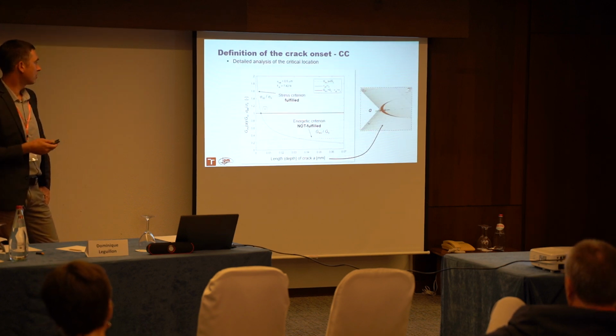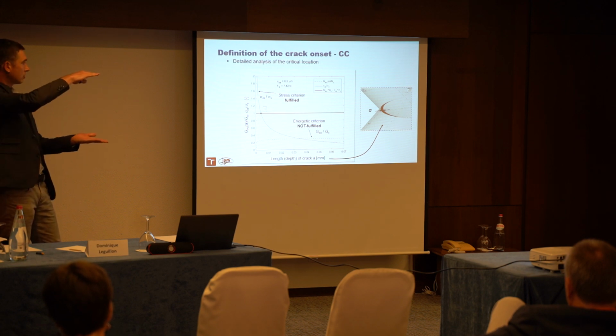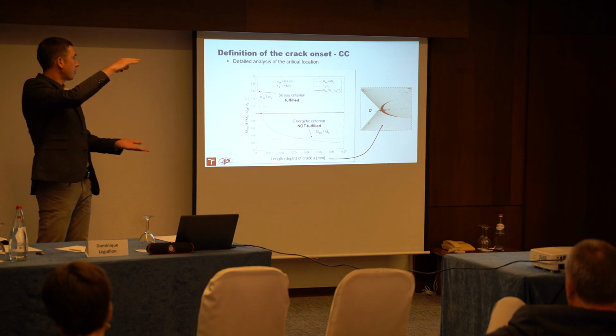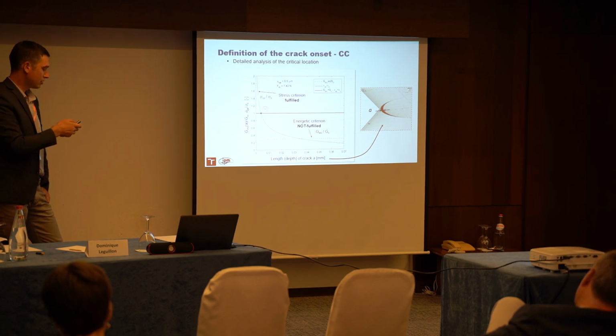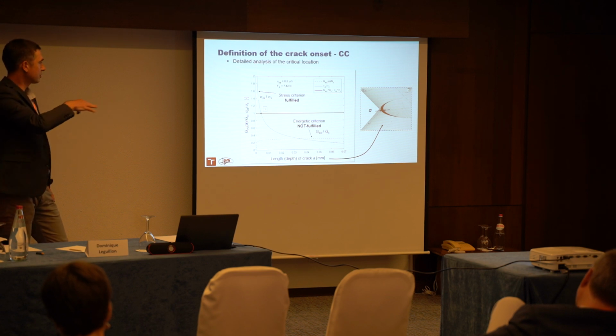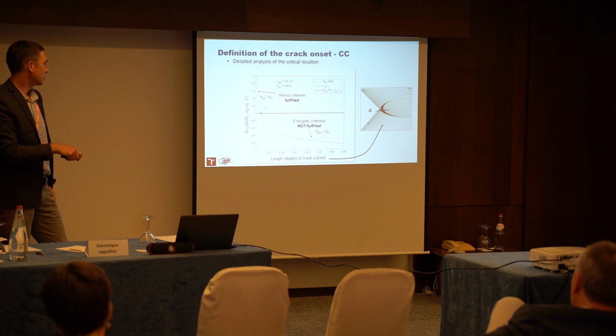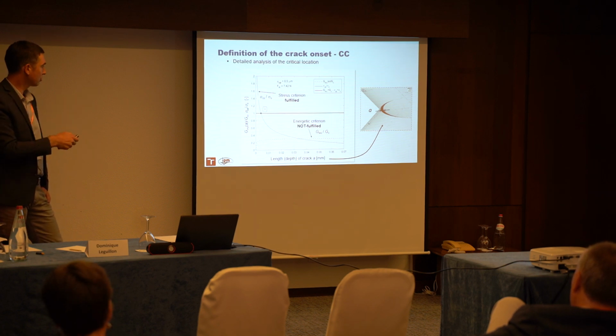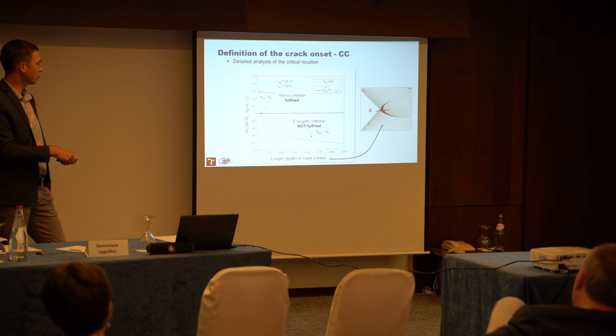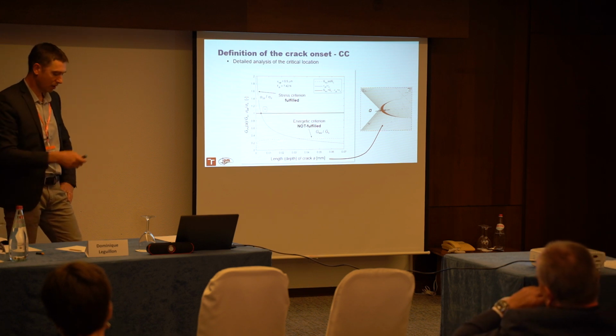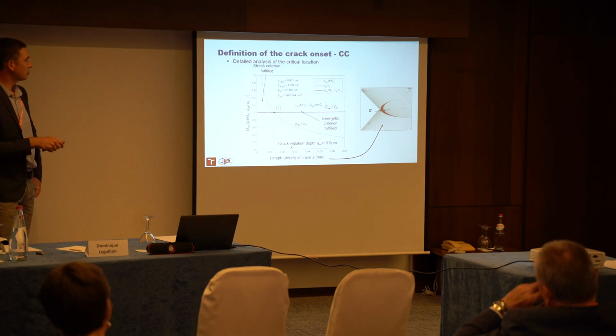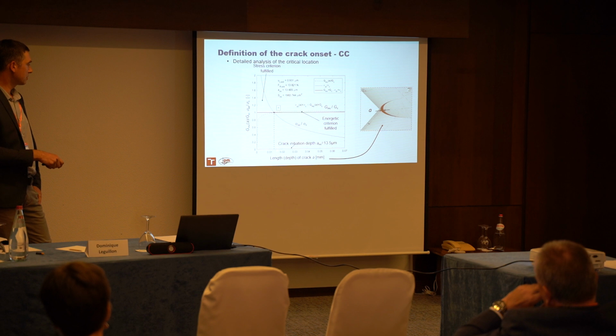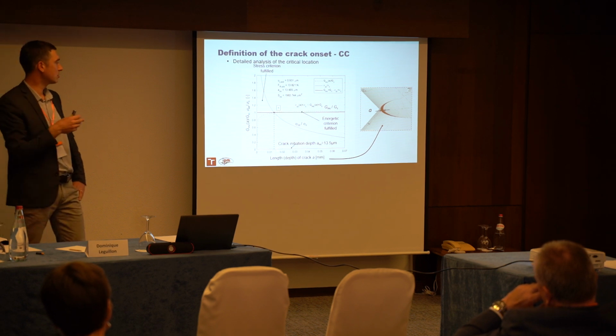So here we applied a couple of criterion. So we loaded the foam structure by some displacement and calculated the energy release rate for different crack depths and also the stresses along the isoline. And this is the result. So here the load was not enough, so we have satisfied just the stress condition, but not the energy one. So we have to increase the mechanical load further up to this point where both of these conditions are fulfilled. So here we fulfill the stress and energy condition, and this will be for us the crack initiation depth A.